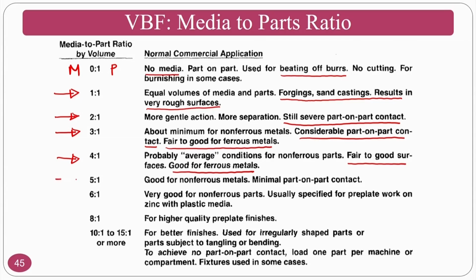So 5:1, if you want to go for this one, there is minimal part to part contact, which means abrasive particles will dominate here. So you will get a good surface on non-ferrous materials also. 6:1 is good for the non-ferrous parts. At the same time, you can go for plastic media also. So that means if your particle volume is very high, you can go for plastic media so that you will get a better surface finish.